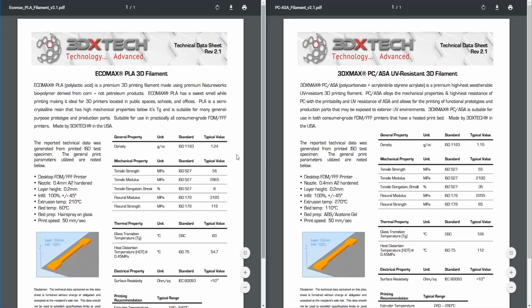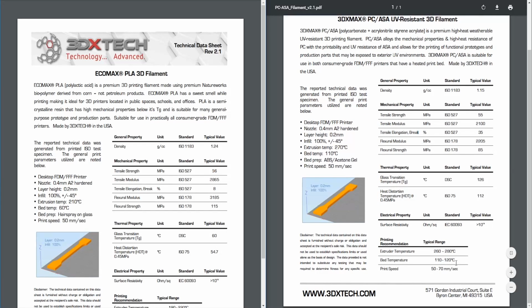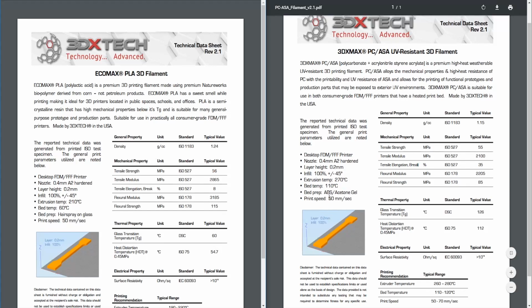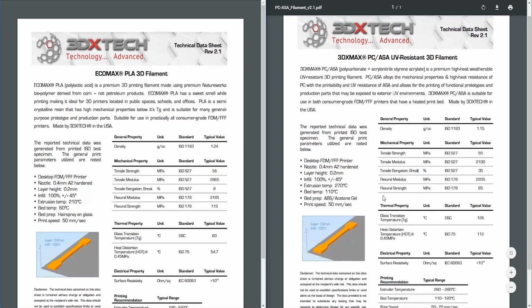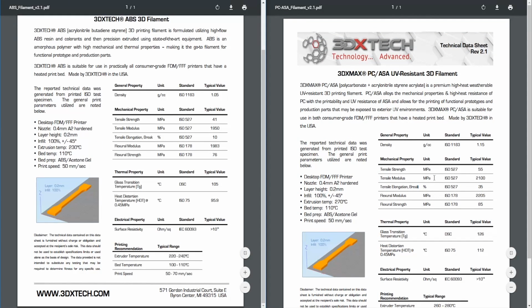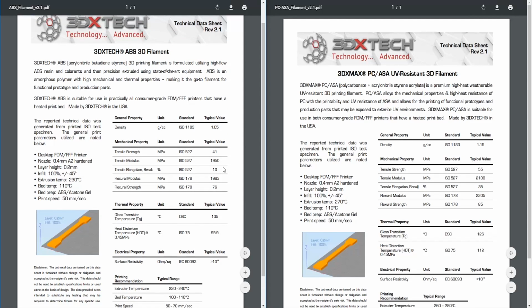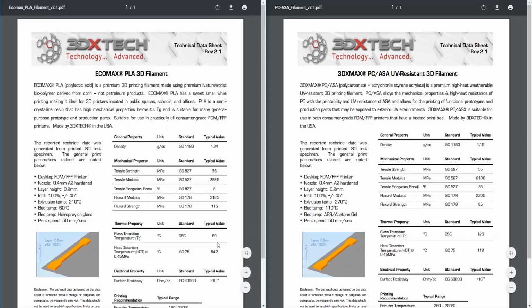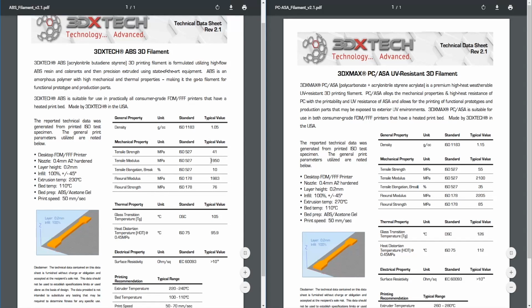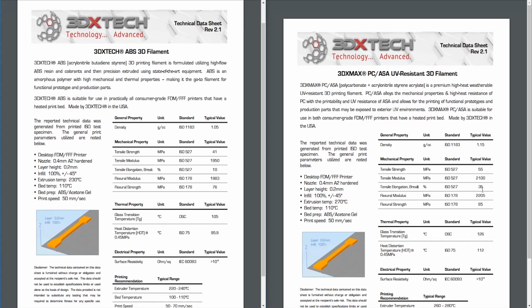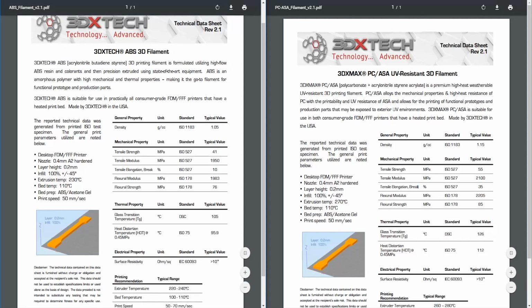Alright, let's go again here. PLA to the next one, polycarbonate ASA. A little bit less strong, a little bit less stiff, 4 times more, a little bit less stiff and flex, and definitely not as strong. And it's almost the same density, and you need a heated bed. So this one, I would say just for the UV resistance, let's compare it to standard ABS, 41 to 55, 1950 to 2100, and obviously it's quite a bit more stable under temperature. 55, 2100, quite a bit stiffer, stronger, more flex, better in flexing. Stronger here, higher. So still better than ABS.